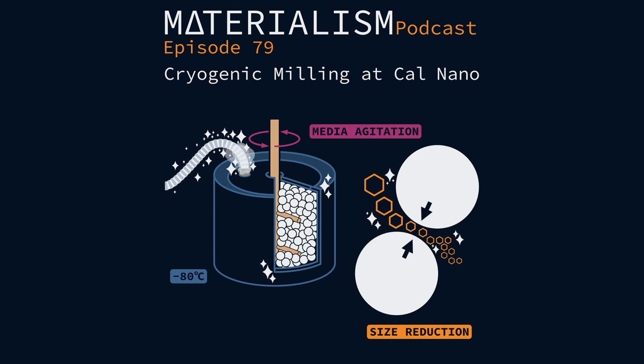But then here at Cal Nano, we take that to the next level. So we do what's called cryomilling, and that's high-energy attrition milling, but at cryogenic temperatures. We're actually introducing liquid nitrogen or liquid argon into the milling process as the medium, and that gives you a whole host of different benefits and processes that you can do there. Now, listeners might be wondering, why on earth complicate this further by adding liquid nitrogen? That just sounds like a whole other can of worms. There's a good reason for it.